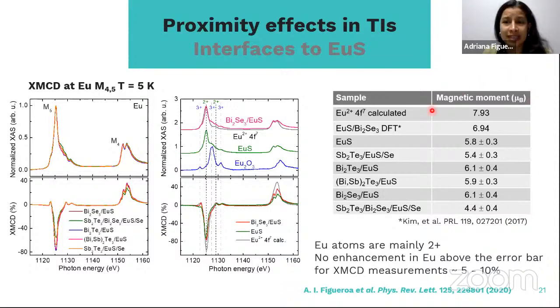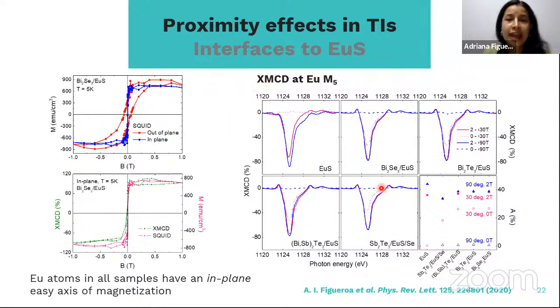We obtained the values for the magnetic moment for the different samples, and we compared them with a reference sample of single europium sulfide. We don't see much difference between what we observe for these samples interfaced with the TI and the reference sample. There's no enhancement of the europium magnetic moment. Also, in terms of the anisotropy, we studied different geometries to see the in-plane and out-of-plane components for the europium sulfide. And we observe that in all cases, all samples have an in-plane easy axis of magnetization, not only with XMCD, but also with regular macroscopic SQUID magnetometry.